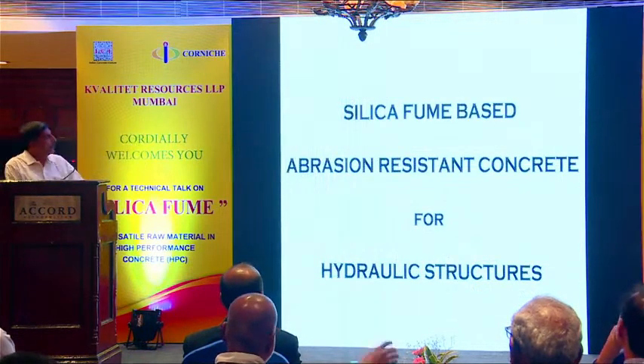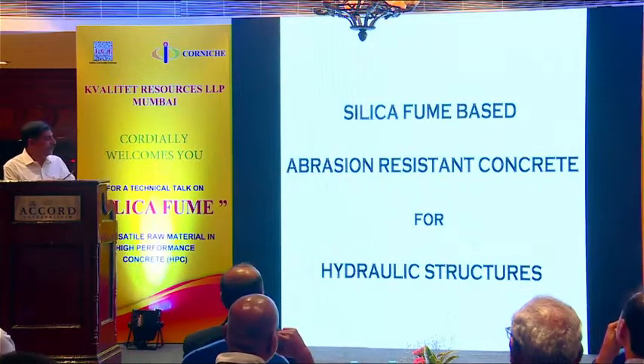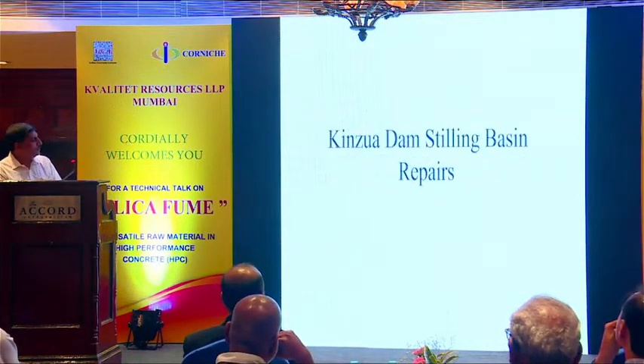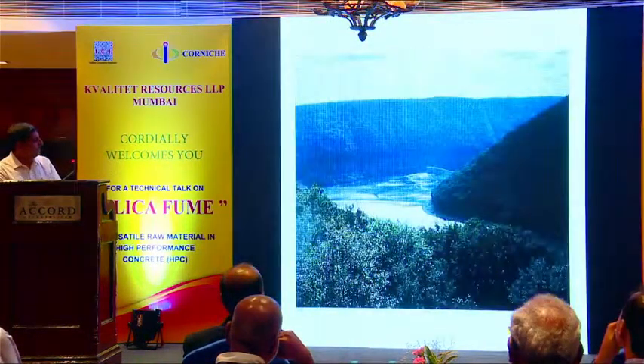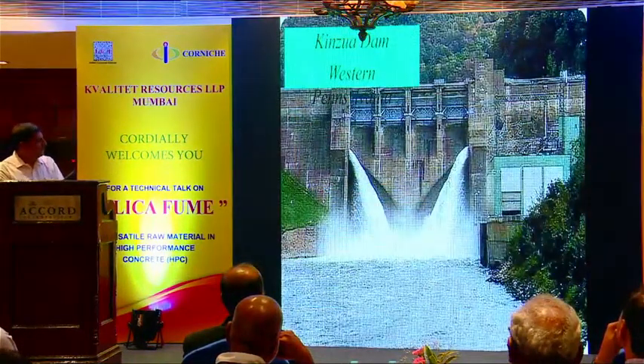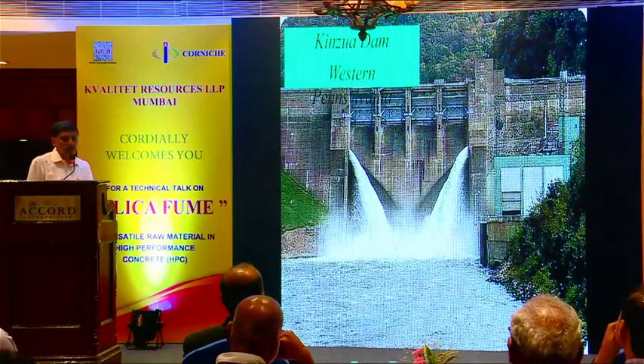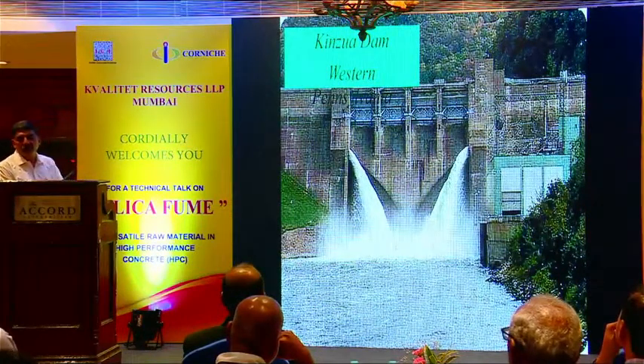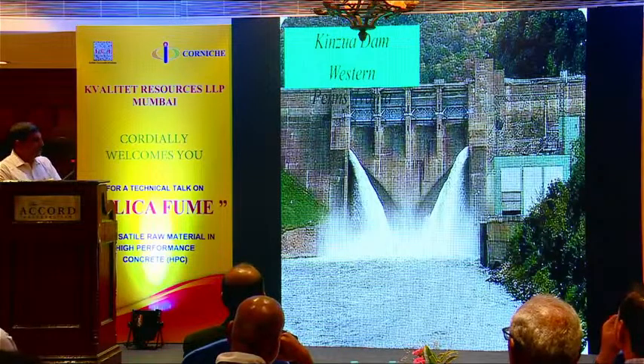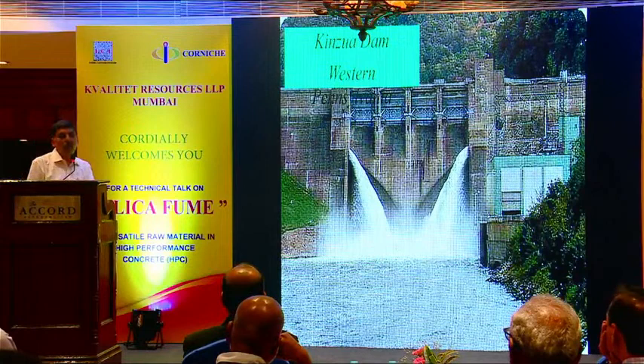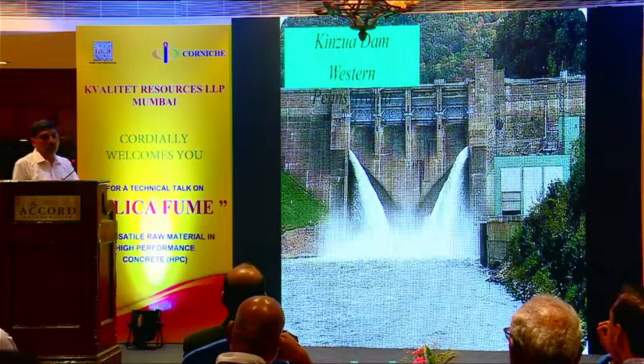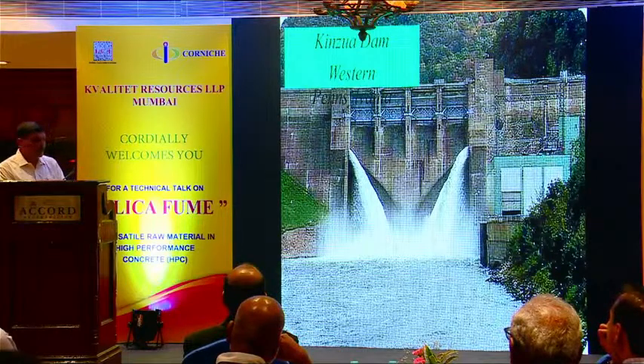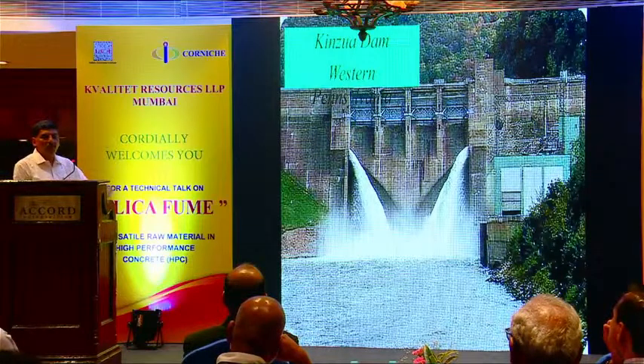So silica fume based abrasion resistant concrete, I showed you about the Kinzua Dam. I'll show some slides. It was built in 1967. It came up for first repairs in 1973-75. The primary conclusion was the aggregates were not hard enough. They were soft, local aggregates. So they decided to import good aggregates from the neighborhood. And the first repair was done in 75. Come 83, 84, the whole repaired portion had eroded.